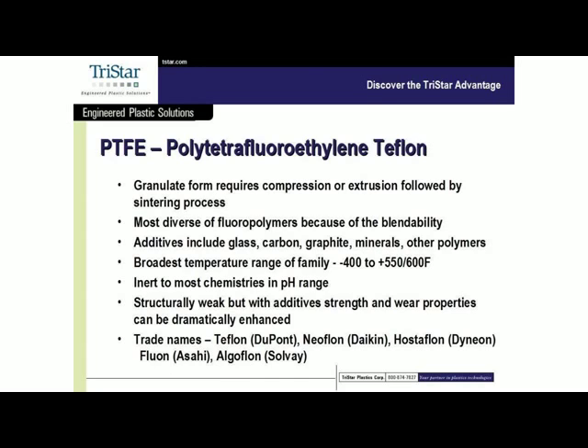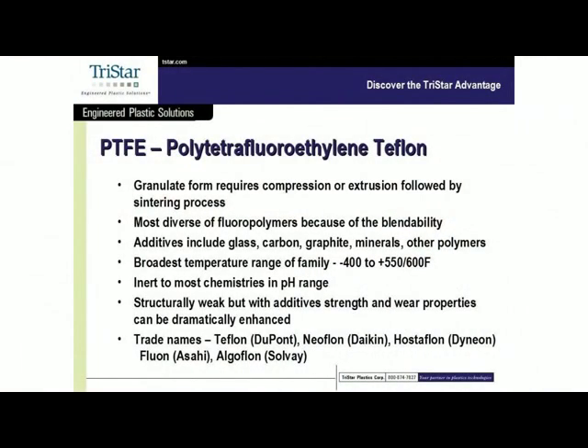Of all the fluoropolymers, PTFE has the broadest temperature range. It will go all the way down to cryogenic temperatures and up to 550, in some cases even as high as 600 degrees Fahrenheit on a continuous basis. PTFE is fully inert. There are very, very few materials that will attack PTFE, and the chemistries that do attack it are actually the chemistries that we use to etch PTFE so that it can be bonded. Most PTFEs are structurally pretty weak, and it's for that reason we have to add the fillers to help strengthen it in terms of physical properties.